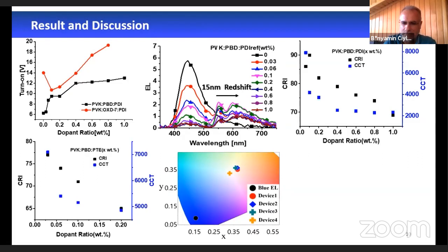The main reason of this is that PDI absorbs the PTE emission. By reducing the PDI ratio, this absorption is also reduced and the white light properties are improved. In this way, there is PTE dominated spectrum in devices 1 to 3, while balanced spectrum is observed in device 4. This device gave CCT and CRI values which are very close to daylight.